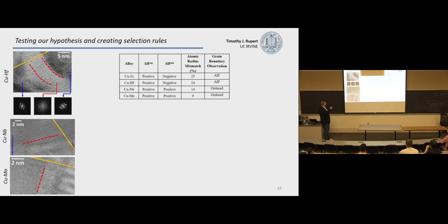You see these big, thick amorphous grain boundaries in copper hafnium, and then in copper niobium and copper moly, you always get these boring ordered grain boundaries. So crystal 1 and crystal 2 are coming right up against each other. So that set of rules starts to work. We're able to see that we need to have segregation. We need to have a negative enthalpy of mixing, and a large atomic size mismatch works.